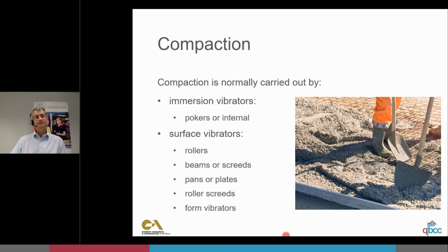And just point out, on fairly thin slabs like pathways or driveways, you get a certain amount of compaction with the shovel and by walking around with your boots. But if you do use a poker vibrator, they're made to be used vertically. If you use them horizontally to drag the concrete around, particularly if you're doing decorative concrete driveways with exposed aggregate, you might end up segregating the paste and the stone, and the finished product will look a little patchy in terms of patches of a high concentration of aggregate and patches with a high concentration of paste. So we need to be a little bit careful about not using poker vibrators horizontally as an aid to moving the concrete around.